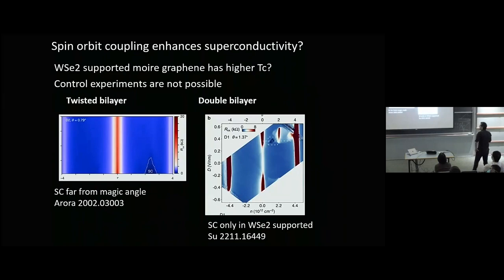Okay, and this is interesting because the history here is that some people study WSe2 for spin-orbit coupling. They get wildly different answers for what happens to the graphene when you put it on WSe2. Some people use it because they like it better as a substrate, and that might be because they think it pins things to make moire systems cleaner and so on. But one of the things that's been interesting is that it seems relatively ubiquitous that superconductivity likes being on WSe2. So for example, in twisted bilayer, you see superconductivity quite far from the magic angle in WSe2 supported devices. In twisted double bilayer, as far as I know, superconductivity has only been seen on WSe2 supported samples.